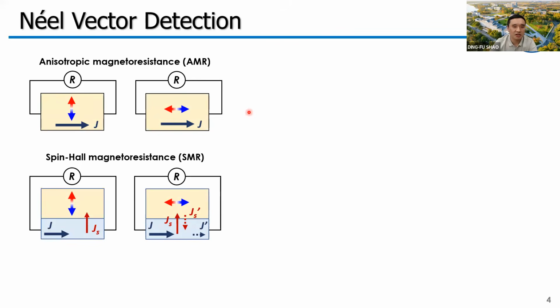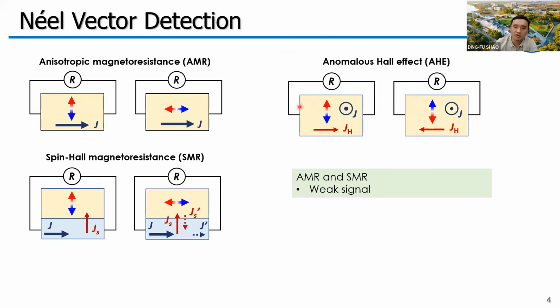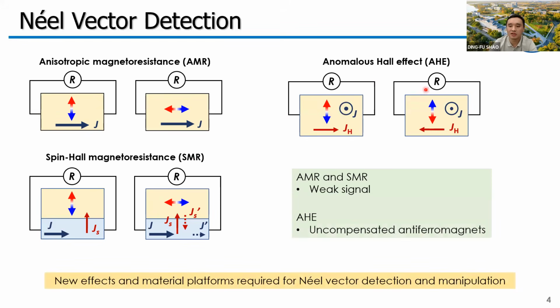So far, the most common methods to detect the Néel vector in compensated antiferromagnets are the anisotropic magnetoresistance and the spin Hall magnetoresistance. These effects are driven by spin neutral current, and the signals of these effects are usually very weak. It will be promising if we can introduce the anomalous Hall effect in antiferromagnets for the Néel vector detection. However, the antiferromagnets supporting the anomalous Hall effect are in fact uncompensated antiferromagnets, which means they should have ferromagnetic symmetry. So the non-vanishing, tiny but non-vanishing net magnetization and the anomalous Hall effect and the spin polarized currents are largely supported by symmetry.